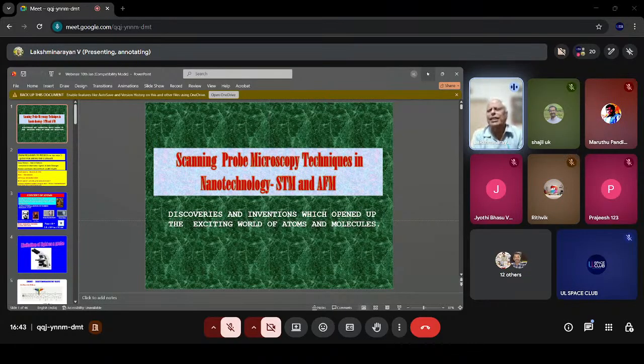Yeah, see, STM, one can do in a matter of minutes, depending upon the scan rate, because scan rate itself is based on the sample. So how fast you want to image the sample. It's not something that we are in a hurry about, so you can actually make this sweep faster. It also depends upon the surface properties. Typically for some HOPG, let us say, it takes about 5 minutes to get an image. And with AFM, you can get an image in the same time scale. But if you want to image some biological samples, you don't need to really tear through the sample using very fast scanning and other things. So you use a correct mode. And the imaging itself, whatever modes you use, again depends upon trial and error.